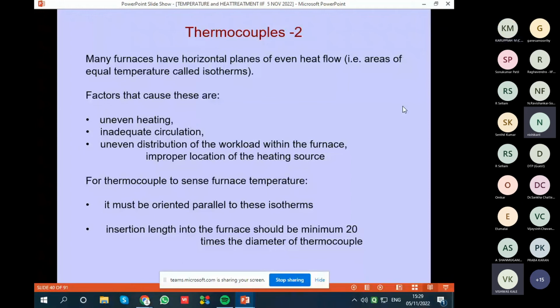So heat may not be reaching everywhere, and the heat capacity of the furnace has to be used fully. If you pack the furnace properly, then possibly the heat transfer will be better. Thermocouples must be put in such a way that they are parallel to the isotherms. Isotherms are the levels of temperature which are uniform.